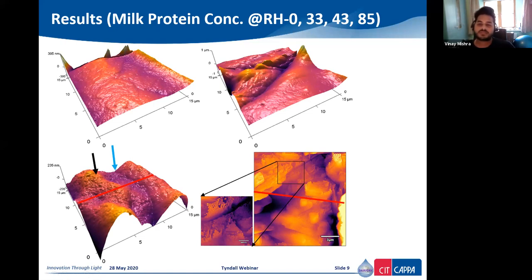Now, they both try to compete for water molecules, and as there is higher protein content, there are changes on the surface due to chemical orientation or different orientation of protein surfaces. Again, there are dimple-like features on the surface which started to appear as a function of moisture sorption. As the moisture content increased, the dimples on the surface started to appear. Also in MPC 85, again, you can see there is formation of lactose on the surface. Now, again, I quickly wanted to mention that milk protein concentrate has a couple of layers of casein network on the surface.